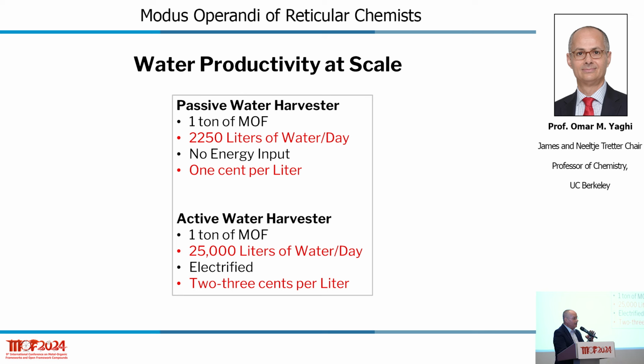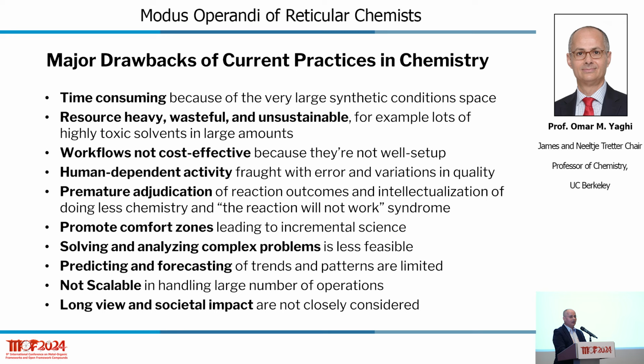Okay, so where are we in water harvesting? This is for 1 ton of MOF. If you're not electrified, you deliver 2,250 liters of water per day, every day for many, many years. No energy input, and so you have 1 cent per liter. If it's electrified, then 1 ton of MOF gives you 25,000 liters of water per day, and at about, depending on the model, 2 to 3 cents per liter. And that's just the beginning. That's just the pre-commercialized model. Okay, so that's the good news, okay?